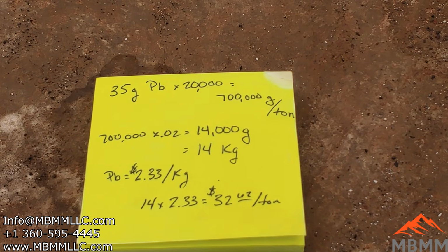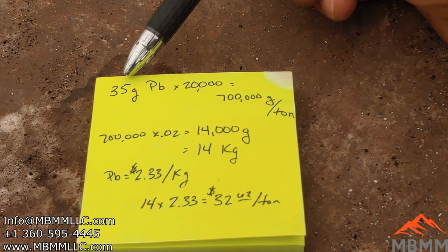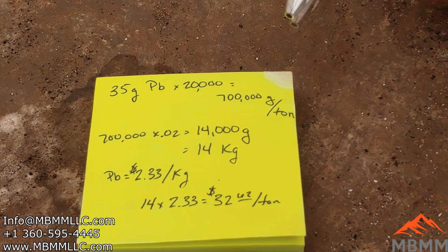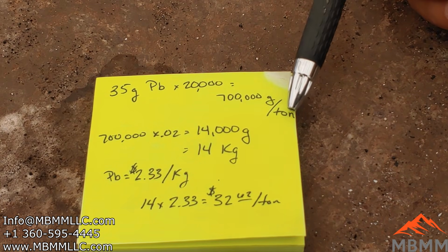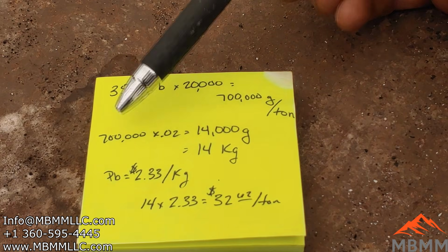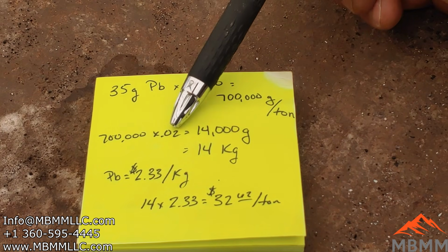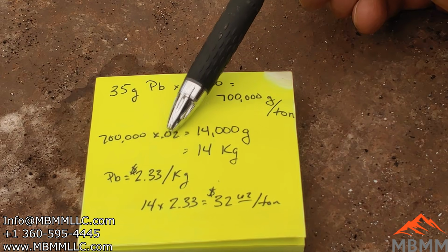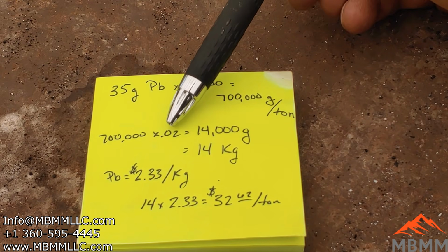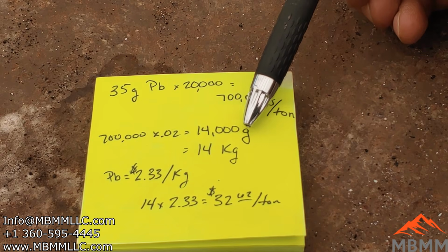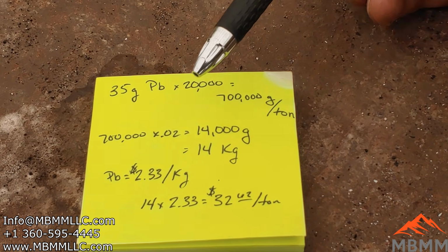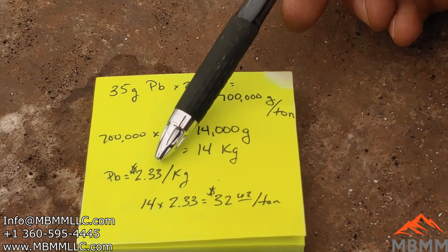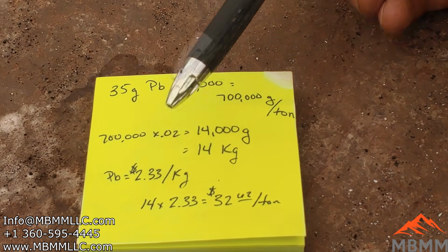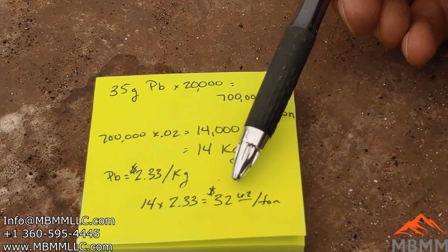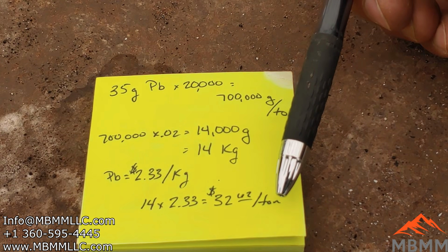So just out of curiosity, I wanted to do the calculation for lead now. We ran our 50 grams, got 35 grams of lead. So 35 times 20,000 is 700,000 grams per ton in our concentrates. But going back to our assumption of 2% cons per ton of ore, 700,000 times 0.02 is 14,000 grams of lead per ton of raw ore. That's 14 kilograms. Lead right now is about $2.33 a kilogram. That ends up being about $32.62 a ton is the value of the lead.